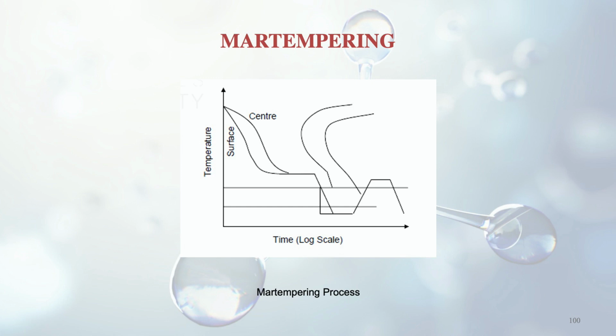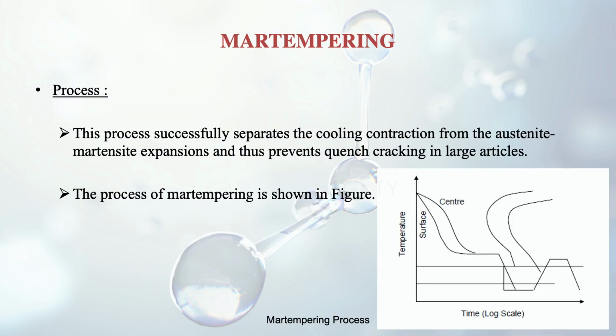Here is the diagram also where the difference is there. If you compare it with the earlier curve on the TTT diagram, for a certain time the line is parallel to the x-axis after the austenitizing process, and then it suddenly moves down below the martensite start temperature, and that's why complete martensite is formed. Whereas in the case of the earlier curve where bainite was being formed, the constant line parallel to the x-axis remains as such, and it does not go into the martensite zone. So this process successfully separates the cooling contraction from the austenite-martensite expansion, and thus prevents quench cracking in large articles. So this is the benefit of this process.